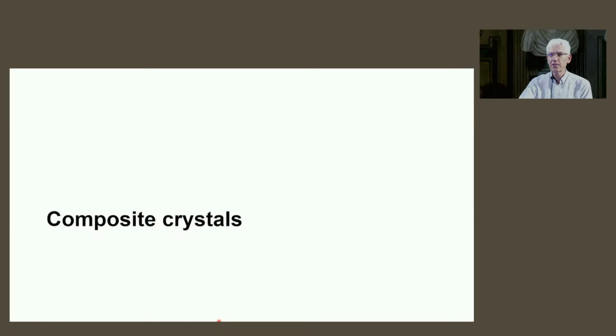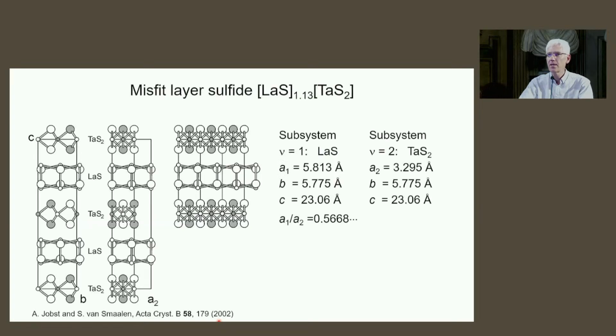Yeah, just a small excursion. Composite crystals, this is a misfit layer compound, and in the left picture you say, okay, that is a periodic crystal because I see a lattice translation B to the right and a lattice translation C to the up, and we have here 1 unit cell. If we turn around 90 degrees, then you say, okay, it's not so good because the third translation, which you don't see in the left picture now, is from left to right, the A, and you see the tantalum disulfide has a short translation, and the lanthanum sulfide has a longer translation.